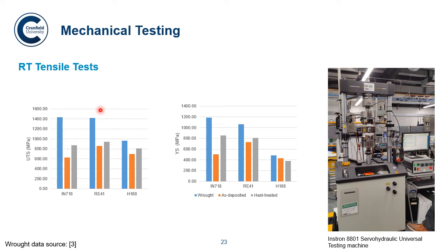Then we see a similar story in RE41. The difference in performance is quite big, not as big as 718, and we think that's due to 718 undergoing quite an extensive aging process to achieve its peak performance compared to the other alloys. And we see H188, which is just our solution strengthened alloy, is the closest to the wrought strength. And it's a very similar story in the yield strength as well. And on the right here is our Instron 8801 servo hydraulic testing machine, which we use to do the tests.